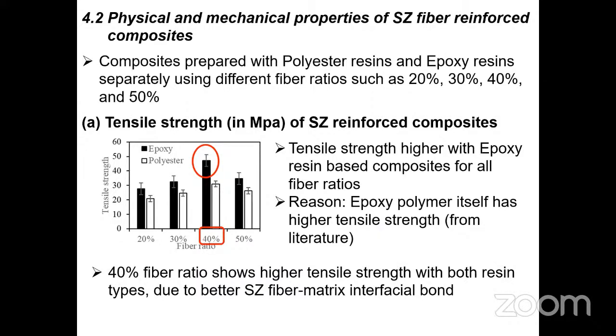The first test we have done is the tensile strength test. Tensile strength is higher with epoxy resin based composites across all fiber ratios, as you can see in the given table. The reason is the epoxy polymer itself has higher tensile strength. The 40% fiber ratio shows higher tensile strength with both resin types due to better Sansevieria zeylanica fiber-matrix interfacial bond.